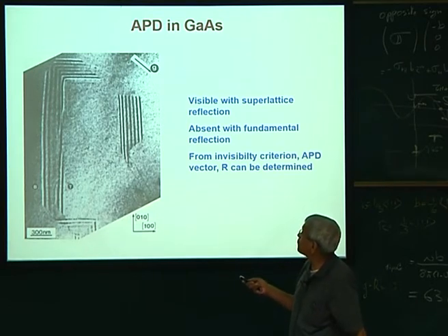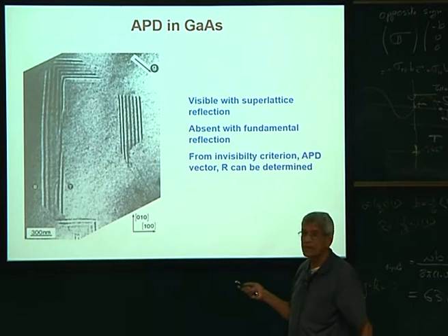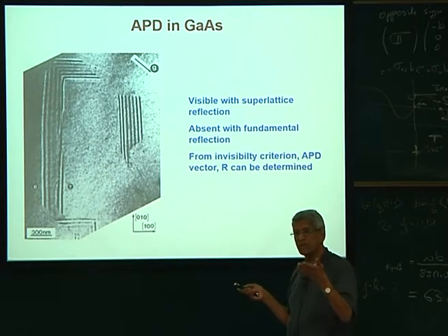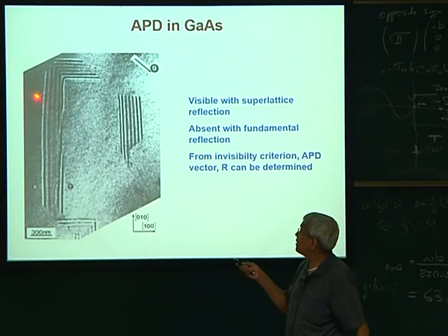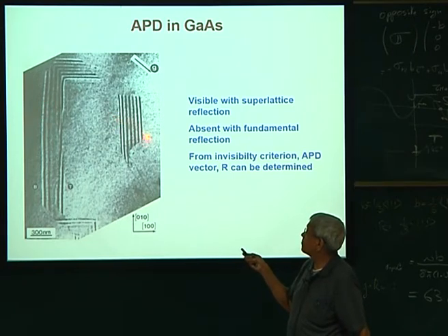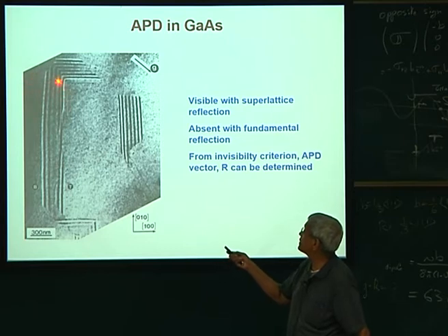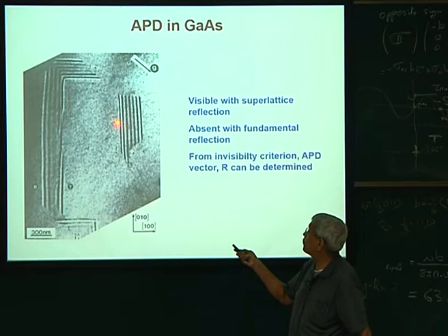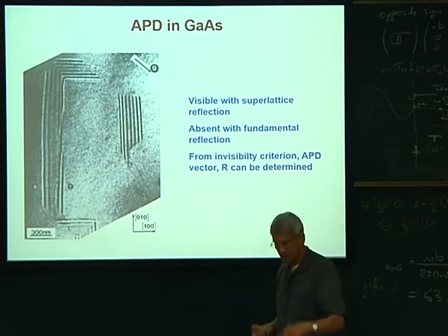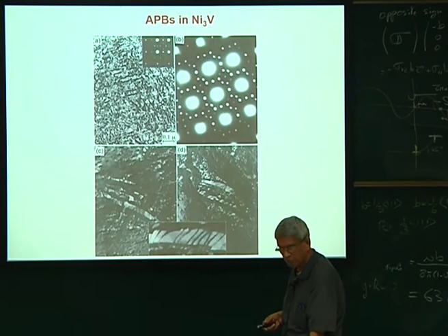And there are some other fine structures as well. In the bright field and dark field images, in a stacking fault we find that one fringe contrast is asymmetric and the other is symmetric. Here both are symmetric, either bright or dark in both of them. If you look at it, the first fringe and the last fringe are the same here. Here also it's bright, and in the other one it's dark. So this is the difference between antiphase boundaries and stacking faults.